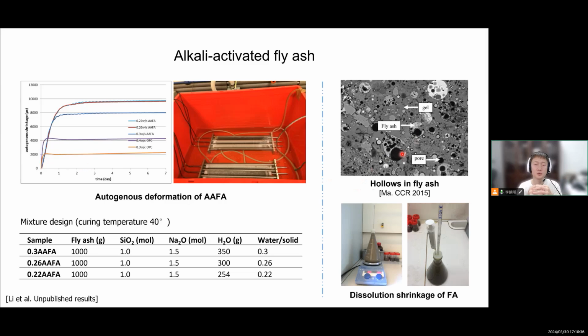And then during the dissolution, the fly ash are dissolved and exposed, so they tend to suck solution back. And then we will find chemical shrinkage. But this kind of chemical shrinkage is more a physical issue. It is not due to the reaction that consumes water, but just the water filling some volume of the hollow voids. So using this kind of simple method, I can experimentally measure how big the hollow voids are.